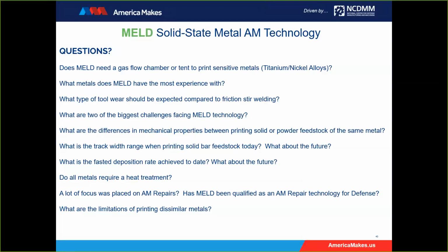That is a great question. Okay, now today we use the off-the-shelf 3/8 inch square feedstock. And with that material, we're able to get track width from a 1/2 inch out to a little over 2 inches. In our roadmap, we go to, I call it the mini MELD, don't have a name for it yet, but it's going to use a smaller square feedstock, probably down to a 1/16 of an inch, maybe a little smaller in the wire range. Of course, that's a new machine. We got to increase the RPMs by a factor of 10 and reduce the linear forces by a factor of 10 so we don't buckle the material. Well, that'll give us much smaller track width.